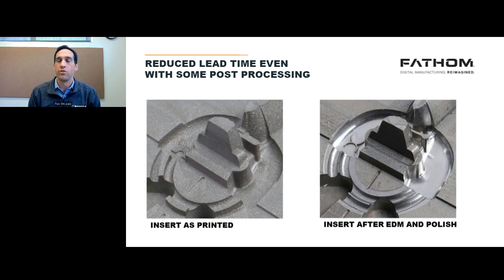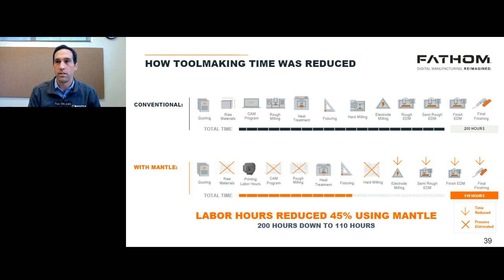And so they were able to do that, whereas when Mantle printed the tooling components, Fathom did the final finishing work. And they still had to do EDM, but it took what would have been 100 hours of EDM down to 27 hours of EDM, and total toolmaker time from 200 hours down to 110 hours. So they're able to really reduce the amount of time from their toolmakers and get that plastic part in the hands of their customers more quickly.